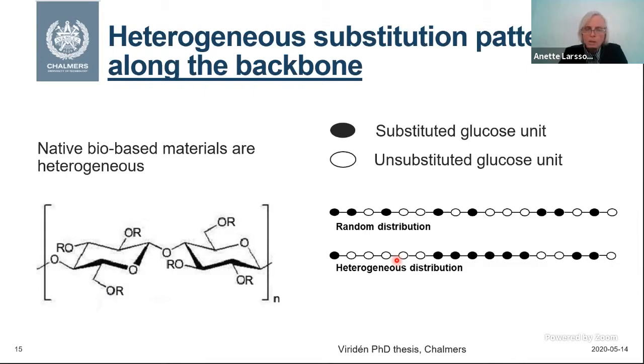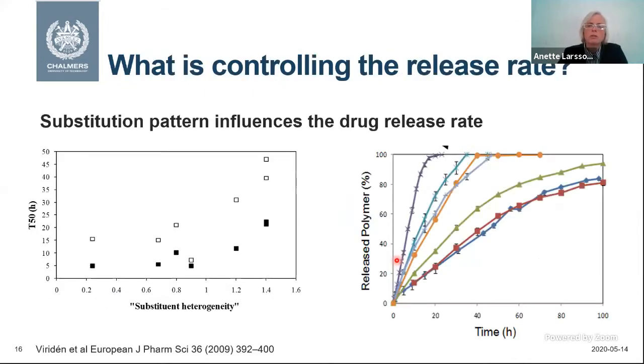So what we did was that we could correlate the degree of substitution and the heterogeneity in the substitution, and that was measured by how many glucose units without any substituent we could find when we treated them with enzymes, and we could compare that to how many glucose units without any substituent we had when we had acid cleavage, so we cleaved them with acids instead. And on this axis, we have the T50 value, and that means when 50% is released.